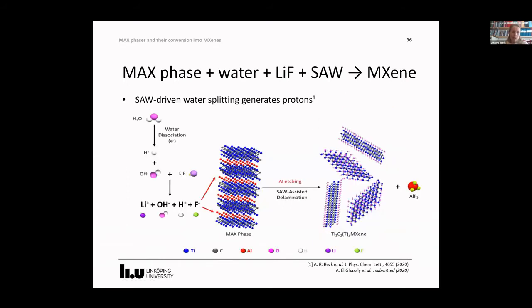It has recently been shown that the electric field accompanying the surface acoustic waves can dissociate water molecules and generate hydroxyl free radicals and protons. And this, combined with our addition of lithium fluoride, generates what could be called localized in situ HF. In other words, local chemistry similar to what we would have if we had used HF.